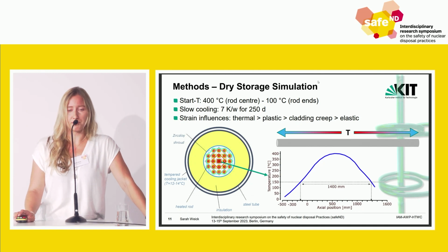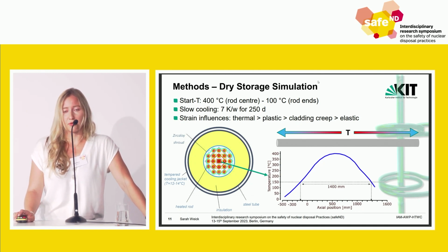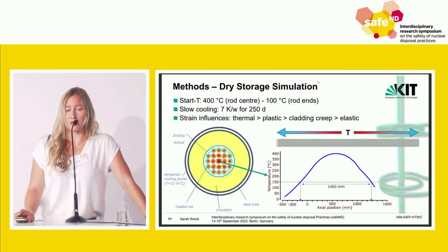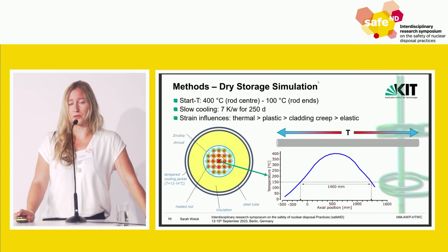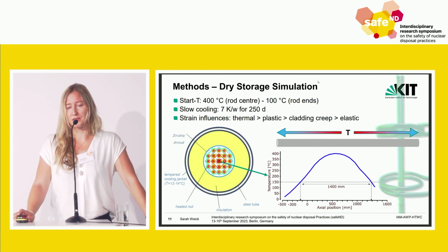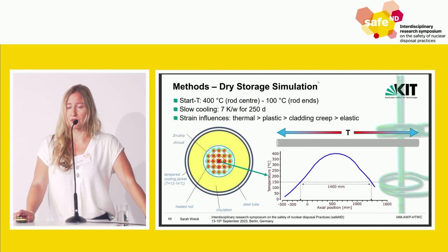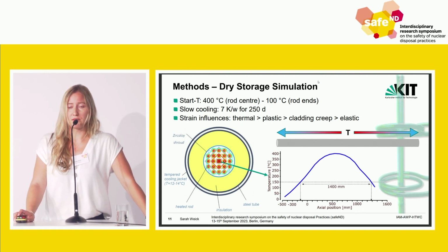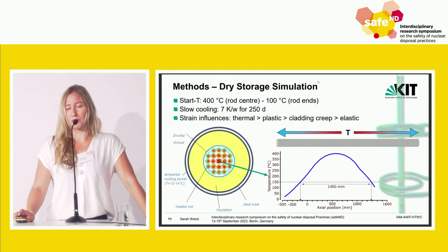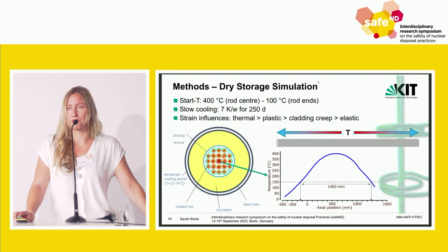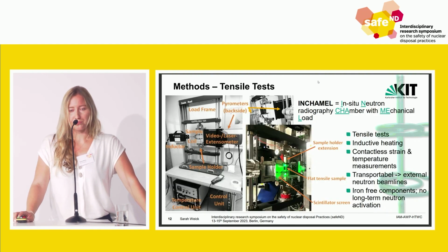So what we expect from those simulations is that we can quantify any strain influences. We expect the thermal influence to be the greatest, then the plastic influence, the cladding creep, and the elastic strain should also deliver some results. We don't expect it to be that great, but still the elastic strain has of course an influence, which we already tried to quantify with some small-scale experiments.